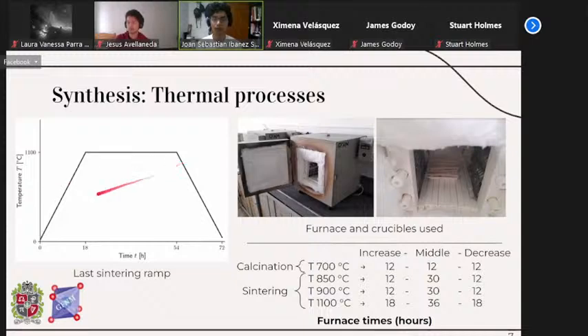At the right, you can see the furnaces that we used, the ones that we have at the laboratory in the Universidad Nacional. It is worth noting that we used alumina crucibles. After each sintering process, we also measured X-ray diffraction and scanning electron microscopy in order to check how the process was evolving. And that's about it for the synthesis.